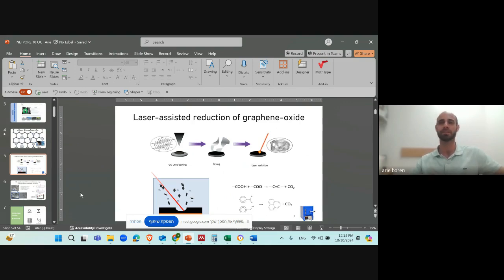So how exactly is it made? The idea is very simple. You just take a carbon precursor. Not all carbon precursors could work, and we'll talk about that later, but you just make a dry film of it, and you just laser it, and you end up with a graphitic film. I'll show you more characterization and images in a minute, but the mechanism is quite simple. The laser that we use is a CO2 laser that simply heats up the sample very fast and very locally. It could reach very high temperatures, up to 2000 degrees, and the carbon is simply carbonized and graphitized into graphene.